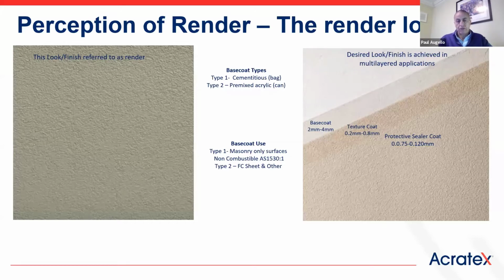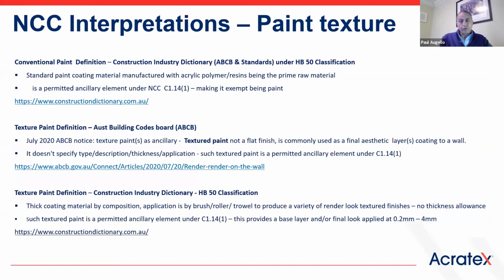Type 2 of a base coat is what we call a pre-mixed material. So this is more of an acrylic material, ready for use. They're only suitable for the more non-traditional materials like fibre cement sheet or similar types of materials. Those materials can't be tested to 1530 Part 1, so it takes it down a different path of where those materials actually sit as a definition. Which leads us into this textured paint interpretation.